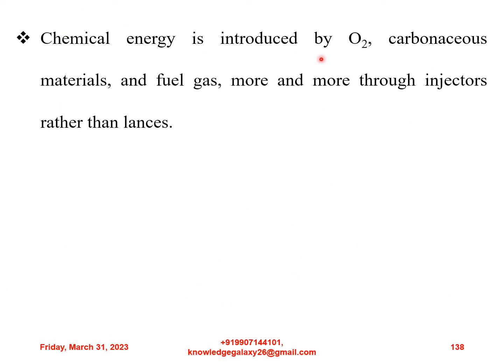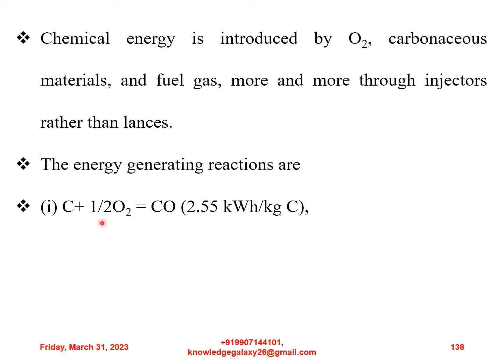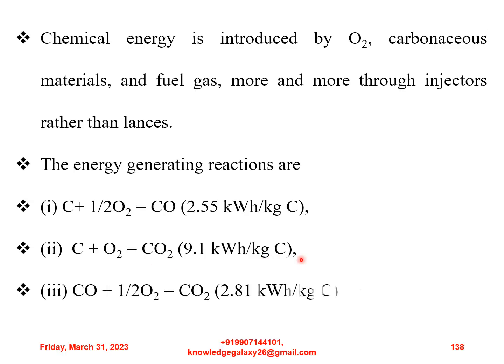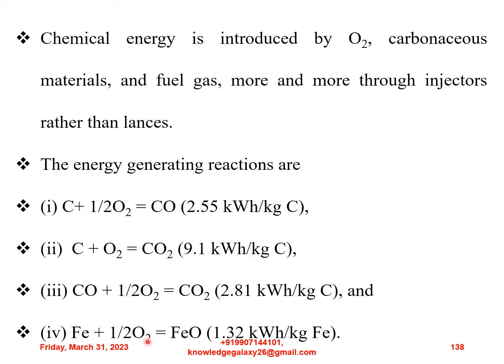Chemical energy is introduced by oxygen, carbonaceous materials, and fuel gases more and more through injectors rather than lances. The energy generating reactions are C plus half O2, this gives CO, and it generates 2.55 kWh per kg of carbon. C plus O2, this gives CO2, generating 9.1 kWh per kg of carbon. CO plus half O2, this gives CO2, generating 2.81 kWh per kg of carbon. And next is Fe plus half O2, generating FeO, 1.32 kWh per kg of iron. I hope these reactions are very clear to you all and you don't have any problem in understanding them.